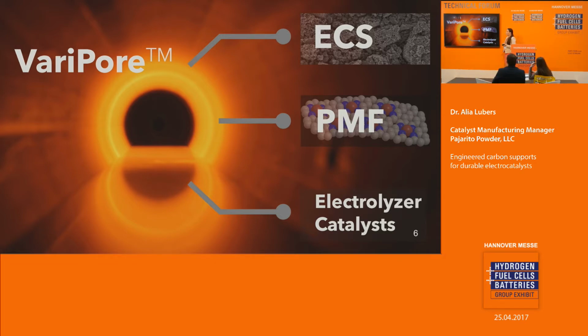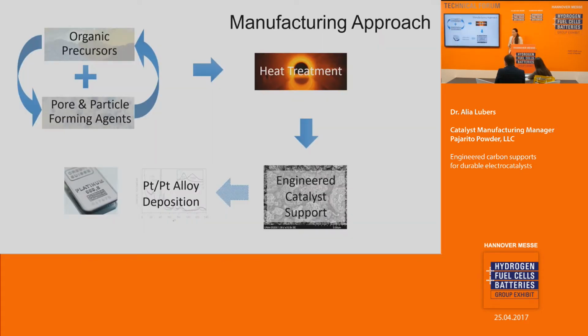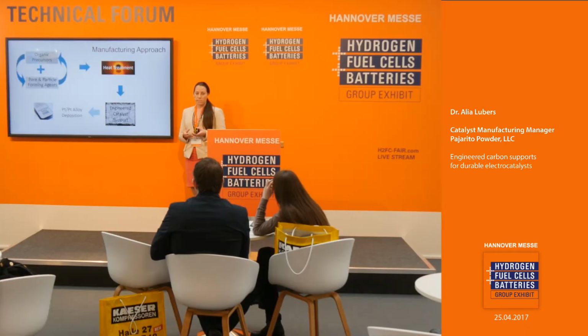We are able to produce three main product lines from our platform. We make engineered catalyst supports, precious metal-free catalysts, which have no platinum, and we also are starting to produce more and more electrolyzer catalysts, although this is fairly new for us. So I'd like to mainly focus my talk today on our engineered catalyst support. Generally, our Varipore method is we will mix organic precursors with pore formers, we'll heat treat that, and most of our materials are made with that basic recipe. We can also optionally deposit platinum or platinum alloys on those materials.